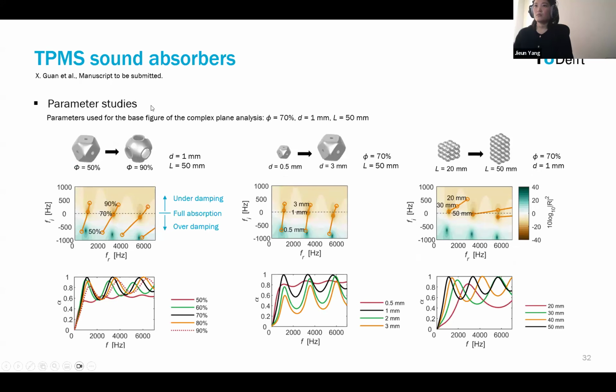And we also did some parameter study by changing some parameters like porosity or unit cell size, and also the thickness of the entire layer. And then we also made this complex plane analysis, which is about obtaining a reflection coefficient in the log scale in the real and imaginary frequency axis. I would not want to go into detail about this complex plane analysis, but there are also poles and zeros